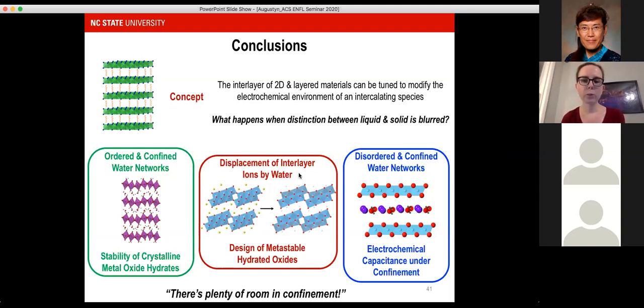So we haven't really seen a solid solution type process, at least not in the tungsten oxide hydrates. And the titanates, we're not sure. We only did a couple of ex situ experiments. But even though the protons are essentially point charges with no mass, their charge does have a significant influence on metal oxygen bond distances. So I think you will see something in X-ray scattering results.